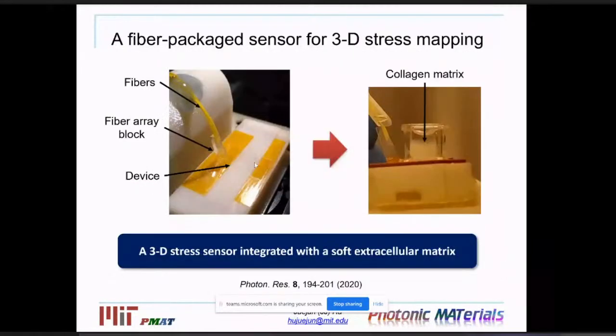Through a collaboration with Xinqiao Jia's group at University, we were able to embed these three-dimensional waveguides into a collagen matrix that's populated with cells. And we were also able to monitor the variation of strain during the growth and differentiation of the cells throughout the entire 2-week period to get three-dimensional distribution of stress during this process. Okay. So if you want to learn a bit more details about the fabrication process of the sensors, I've included the reference here, and we are expecting to publish our results on the three-dimensional stress monitoring pretty soon.